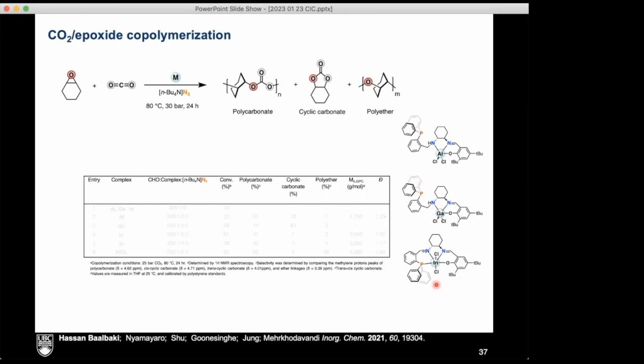So when Hassan compared these complexes, he saw that in the absence of an external nucleophile, nothing happens. So they're not active in the absence of a nucleophile. But when you do add a nucleophile, in this case, tetrabutylammonium azide, he was able to get reactivity with aluminum, gallium, and indium, but indium was very much more selective, both more reactive and more selective for polycarbonate, which is what he wanted to work with. He played around with the reaction conditions a little bit more to really increase his polycarbonate selectivity in these cases.